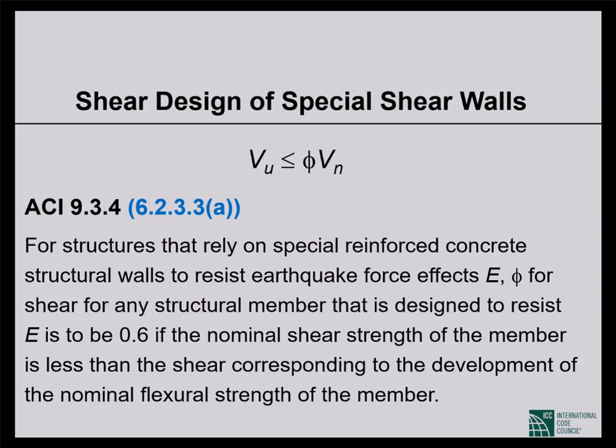So height to length ratio beyond 2, you are looking at flexural failure preceding shear failure, in which case you do not have to reduce the phi to 0.6. I see a lot of people use phi of 0.6 for all shear walls, even with height to length ratio of 5. That is a total waste of money. Okay, so beyond height to length ratio of 2, you are not required to, and you should not use a phi of 0.6. If you don't feel comfortable with 2, maybe go to 2.5. But beyond that, it does not make any sense whatsoever to use a phi factor of 0.6 in shear design.